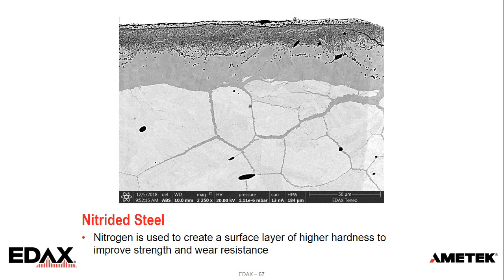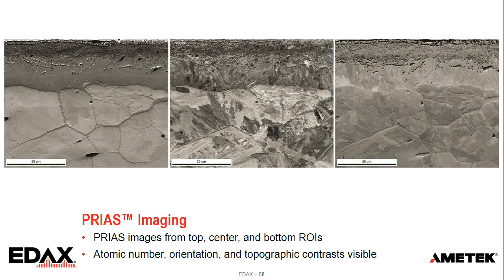And so to characterize this with EBSD, the first thing I looked at is what we call a PRIAS image. PRIAS uses different regions of our detector to create different contrast mechanism images. So you can see on the left, we're getting atomic number contrast. In the middle, we get more orientation contrast. On the right, we get more of a topographical contrast. That's, again, just selecting from the top, center, and bottom of your EBSD detector to monitor the signal in those regions to create those images. So we get some nice pictures of the microstructure with PRIAS.